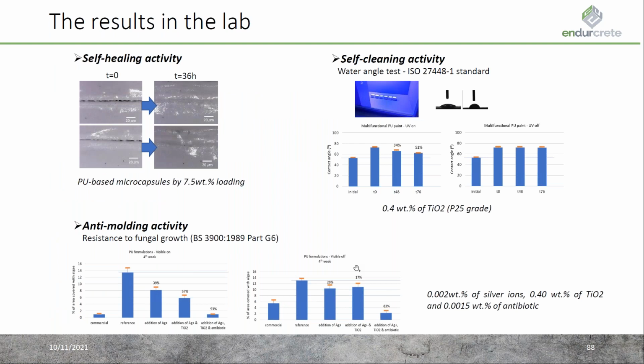The developed multifunctional formulation was evaluated in the lab regarding the self-healing activity by scratching the coating and observing the healing of the gap for 36 hours with an optical microscope. As you can see on the top left of this slide, there is a total healing after 36 hours in room conditions. And the polyurethane-based microcapsules loading was 7.5 weight percentage.